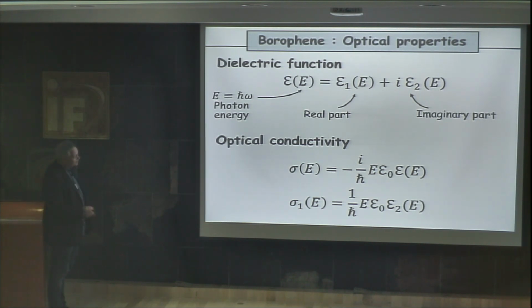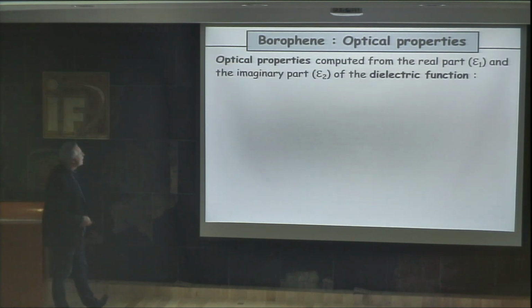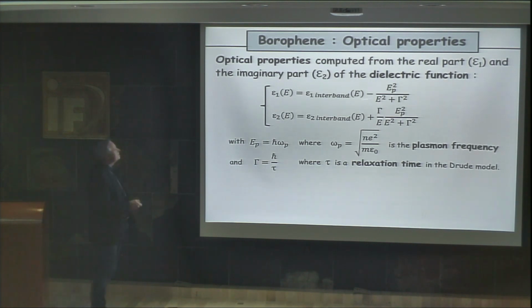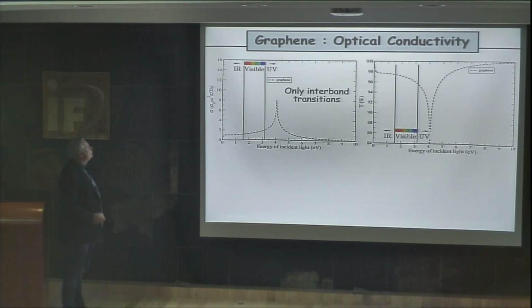So if we want to have access to the real part of the optical conductivity, you need to use, in fact, the imaginary part of your dielectric function. I don't want to go into lots of technical details, but this interband contribution comes from the band structure, where you look at which transitions are possible in Borophene. The second part, coming from the Drude model, especially for the imaginary part of the dielectric function, requires a relaxation time, which leads to an electronic mean free path. This electronic mean free path corresponds to the distance that electrons can, on average, travel between two scattering events. For the rest, it's too technical.